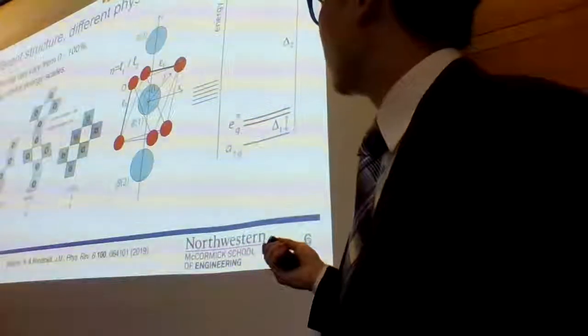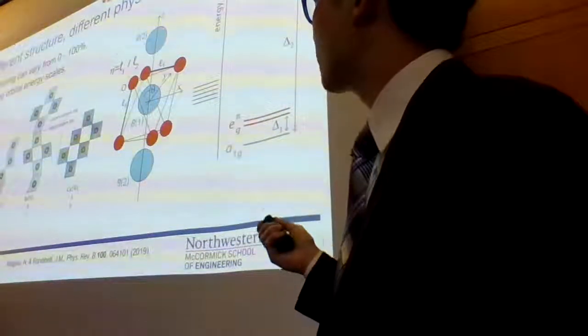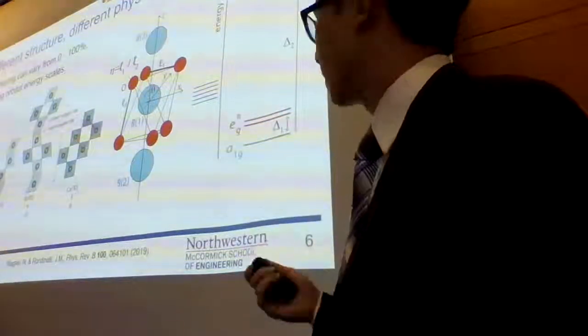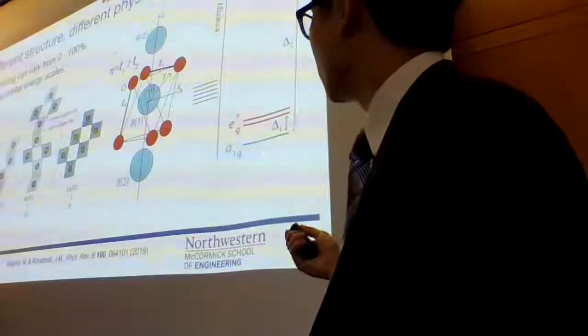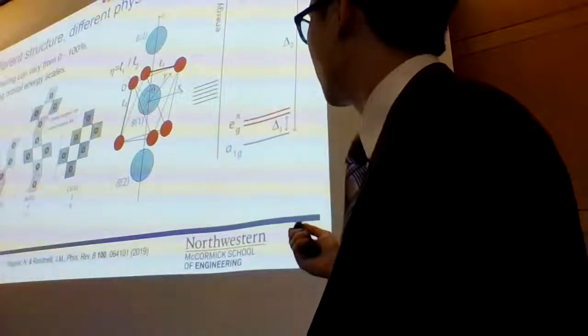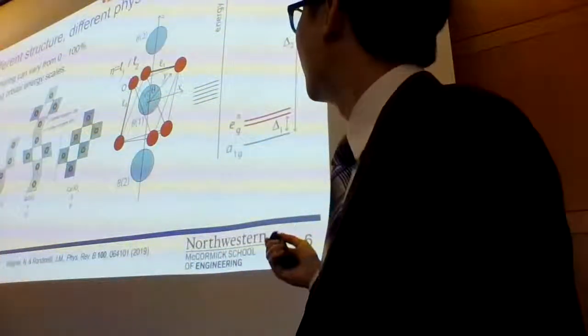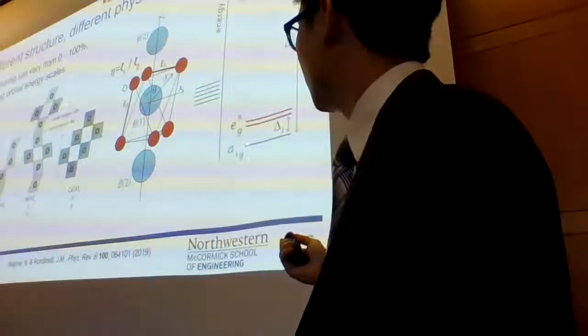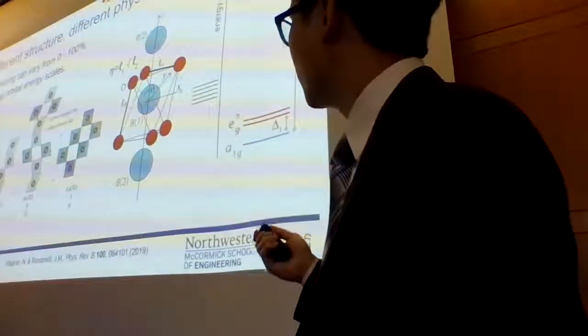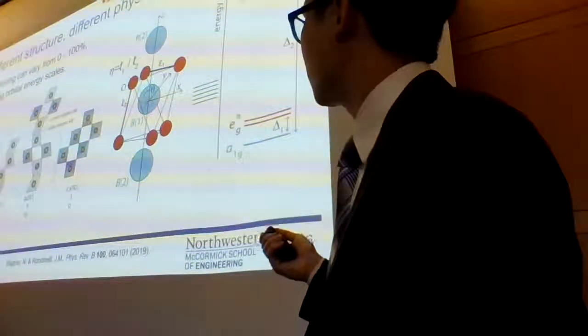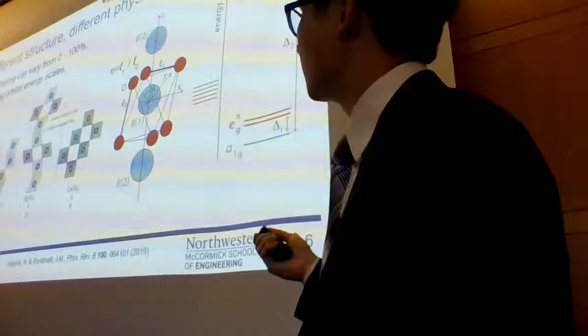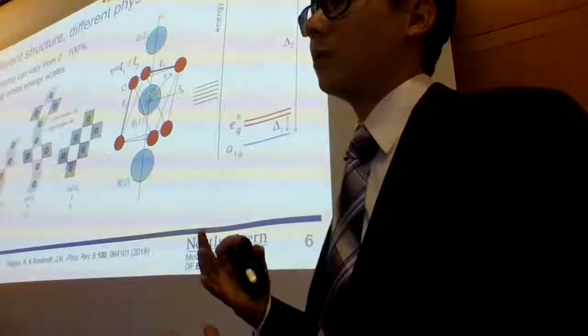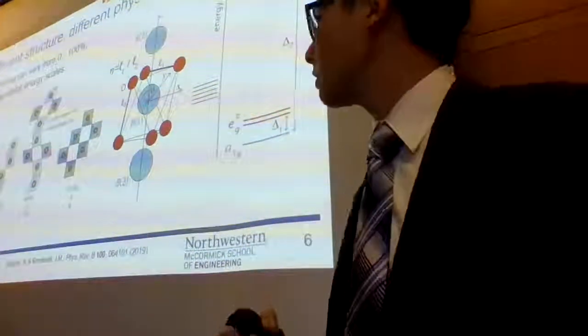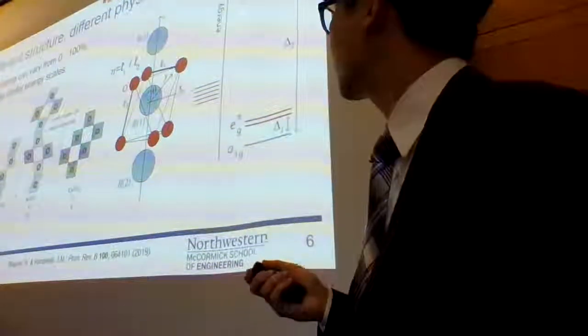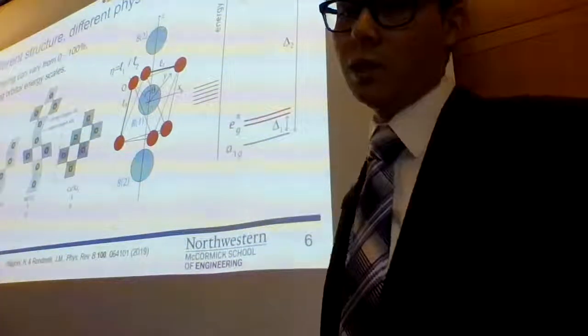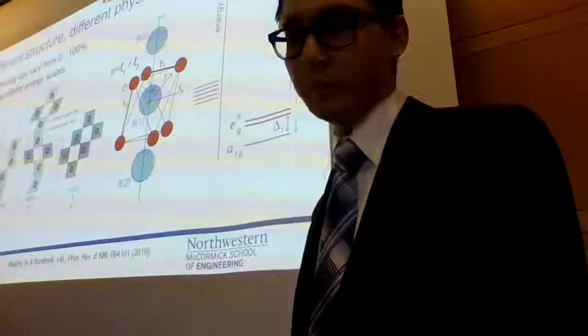And one of the interesting things about this arrangement where you're stacking chains of MO6 octahedra on their faces is that unlike in the traditional cubic perovskites where you have the triply degenerate T2G energy levels on the bottom here, you actually have a further splitting between an A1G orbital pointing along these chains and then EG pi orbitals, which are pointing to the faces of these octahedra. So you have an additional complexity in the physical properties of the system that you don't get in these typical cubic perovskites. And then you also have your traditional EG sigma high energy orbitals as well.